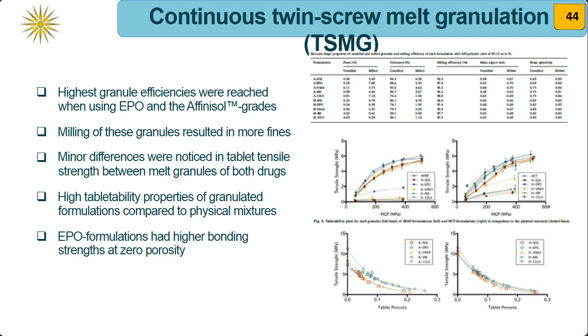As you can see, for all the different polymers there was no significant difference in the tabletability, but when compared to the physical mixtures of the powder blends, we see a substantial difference. The porosity of the obtained tablets was also quite identical, again for both drug substances. We didn't observe any differences. There was a small difference in the paracetamol porosity, especially for the EPO formulation, where they had a higher bonding strength at zero porosity.